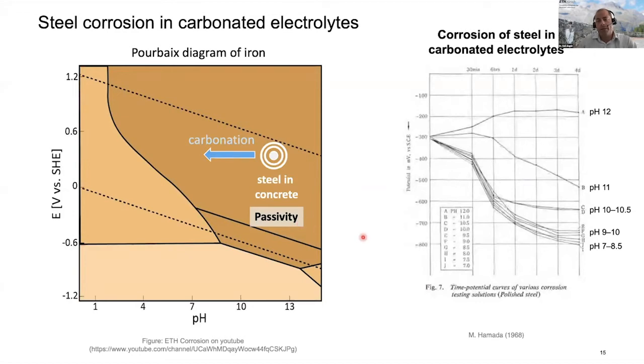This was very early also experimentally demonstrated in experiments in Japan. Hamada reported in 1968, but actually the experiments were done much earlier than that, so they are almost 100 years old, in fact, where steel bars or steel electrodes were immersed in different electrolytes that simulated concrete in alkaline condition, pH 12, or in an increasing degree of carbonation with increasingly lower pH values. And you can see the potential that was measured here over time clearly indicated that when we decrease the pH towards values in those simulated systems around 8, 9 or so, corrosion initiated.